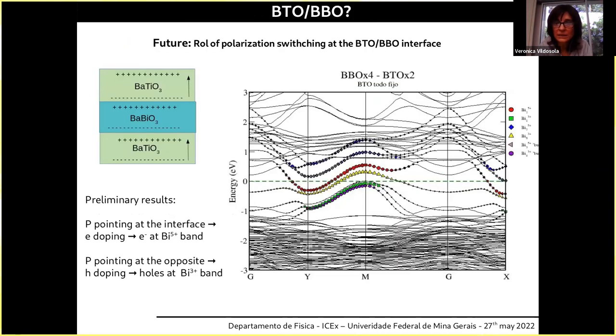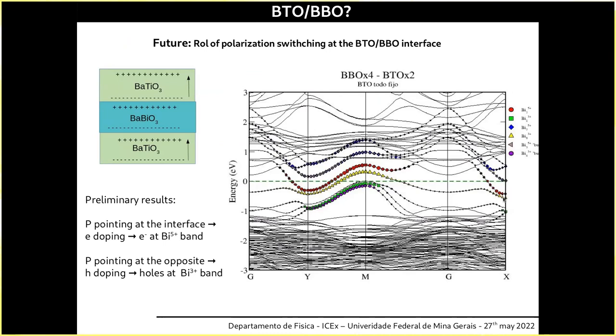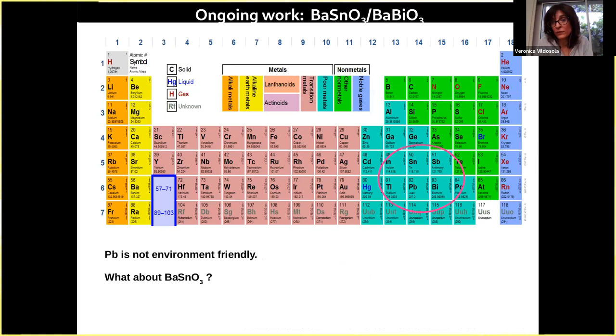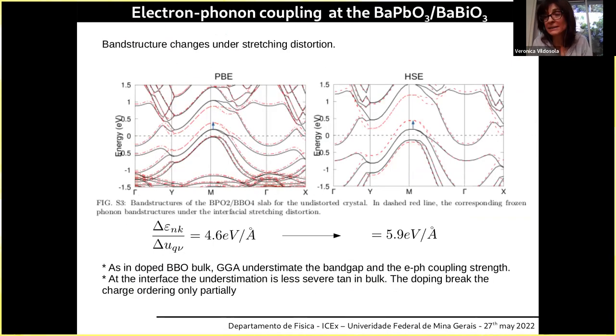I didn't put any preliminary results. Similarly, this happened when we put some ferroelectrics. Here, with some ferroelectric, we can hole dope bismuth 3+ and electron dope bismuth 5+. So using a ferroelectric option, you dope both bismuths, and with a metallic option that was the BPO, you can't do that. With BPO, I don't know exactly why, bismuth 5+ rather stays empty. So here you see the bismuth 5+ is the pocket here, around the X point.